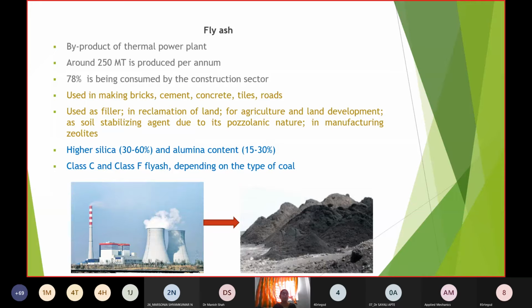So if it is a subbituminous coal, I'll be able to produce class C fly ash, and if it's a bituminous coal, I'll be able to produce class F fly ash, and the quality of fly ash also keeps on changing. So I should take care of what type of fly ash it is and what is required to enhance its properties, so that I can make the best use out of the fly ash, which mainly constitutes 30 to 60% silica and 15 to 30% alumina as its major components, and can be used as the best replacement for cement.